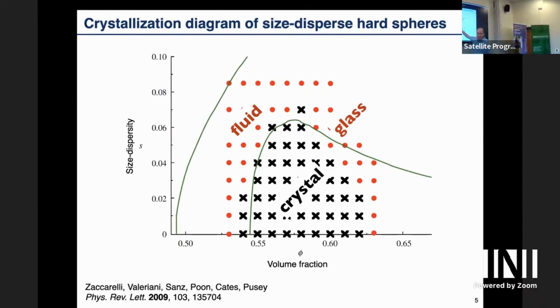Here you will see similar diagrams like this a lot. Here you have the volume fraction, that's the percentage of space that's filled with material. Typically, as a rule of thumb, at 50% is where things start to order, and that's independent of the shape or the composition. It's pretty universal at roughly 50%, sometimes at 60%, but in that range. So here's how dense you pack space, and here is the dispersity. For those that know the hard sphere model, they will know this axis.